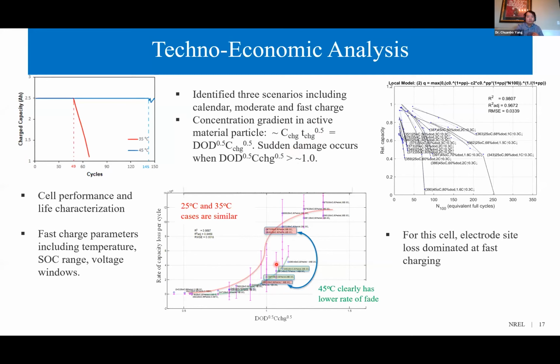The middle figure shows the rate of capacity loss per cycle as a function of the concentration gradient, captured by a sigmoid function. Around concentration gradient 1, sudden damage occurs and the rate of capacity loss significantly increases. Sorry for the red box, but this is a perfect testing condition for comparison. With fast charging at 25 and 35 degrees Celsius, the loss rate was similar, and at 45 degrees Celsius a low rate of fade can be achieved.